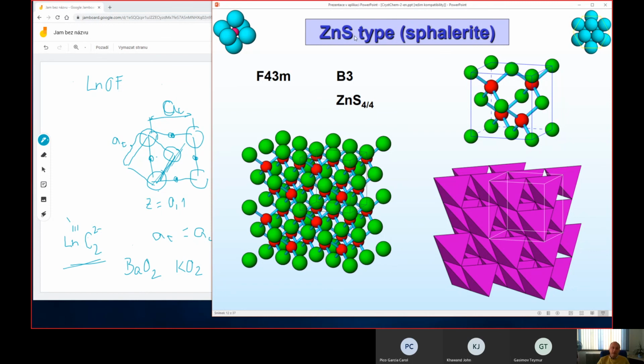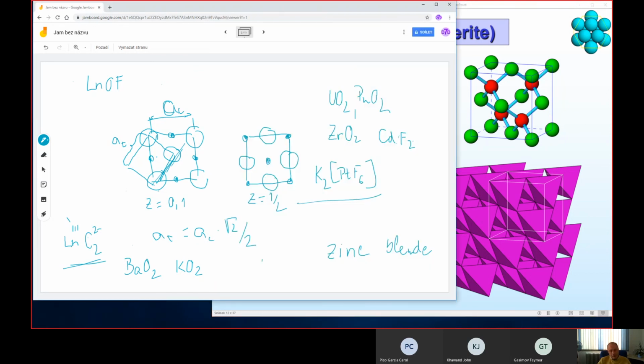And in zinc sulfide, it is the same. These compounds are sometimes referred to as A2B6, because the anion, the B atom, like sulfur or other chalcogen, has 6 valence electrons, while zinc contributes 2 electrons, and 2 and 6 is 8. Which is the same as for diamond or silicon.